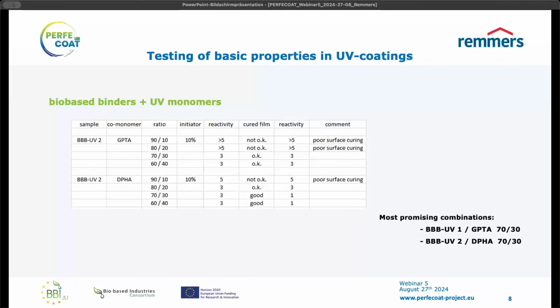So from this test series, in the end, we got 2 favorite combinations. The bio-based binder number 1 in a 70-30 mixture with a trifunctional GPTA, and the bio-based binder number 2, again in a 70-30 mixture with a hexafunctional DPHA. You can see here that the surface of binder number 2 with DPHA is described as good, whereas the previous one was just okay, especially in terms of mechanical resistance.